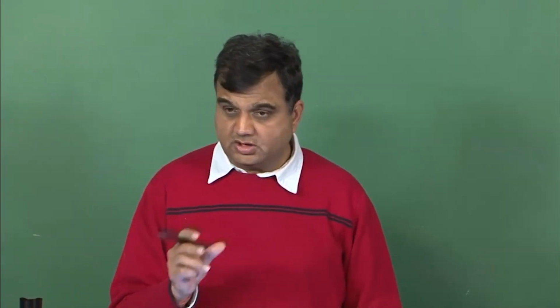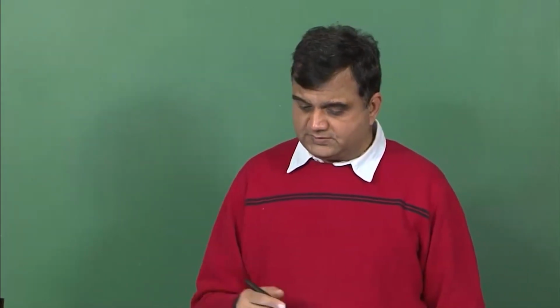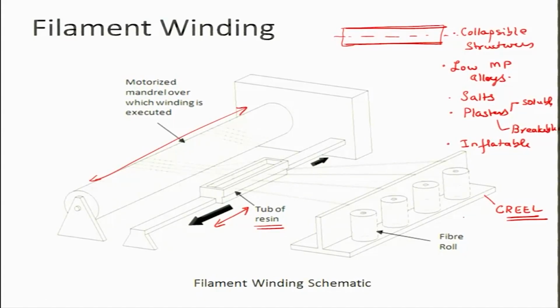You cannot have this with short fibers, and you can have this fiber winding in different patterns. You can have fibers which are wound like this. When will this happen? This happens when the tub of resin's velocity is extremely small. If it is extremely small, then the fibers which wind around the mandrel will be more or less at 90 degrees to the axis of the mandrel. This is called hoop winding or circumferential winding.